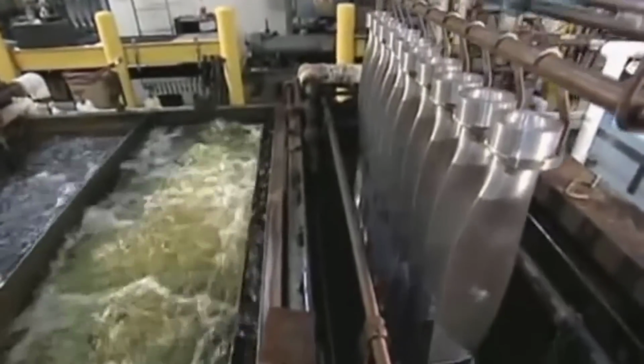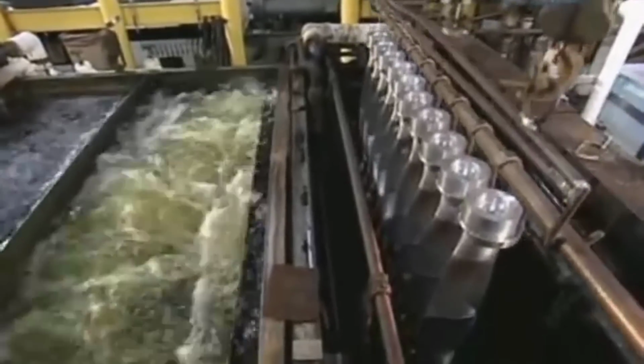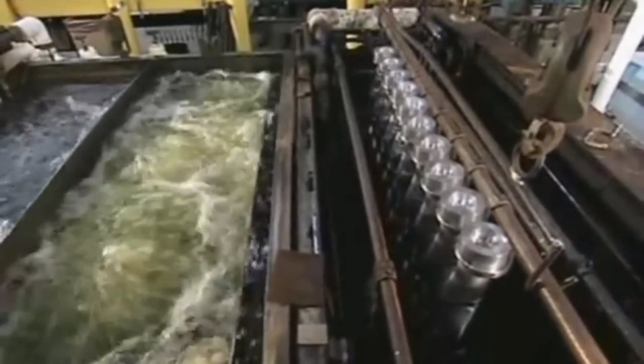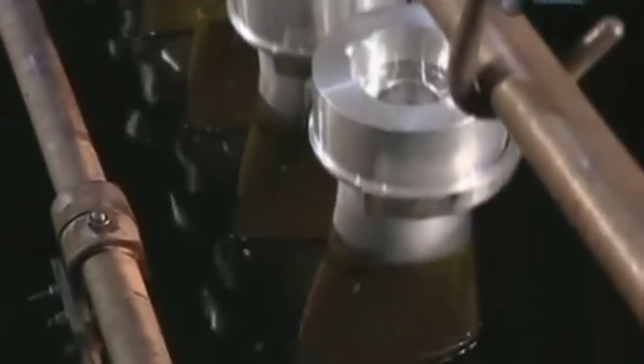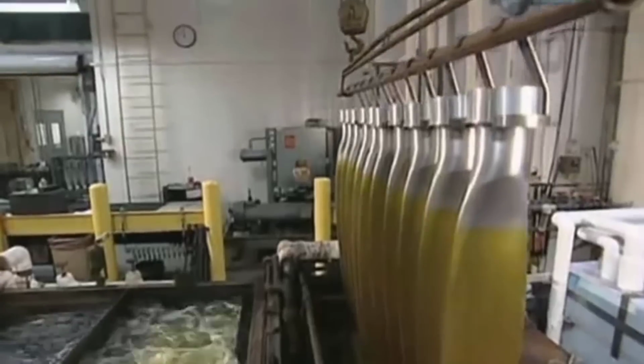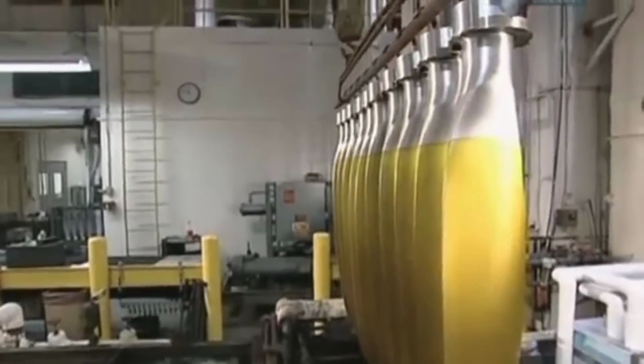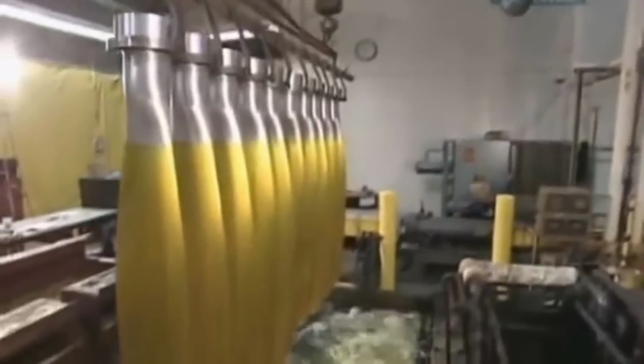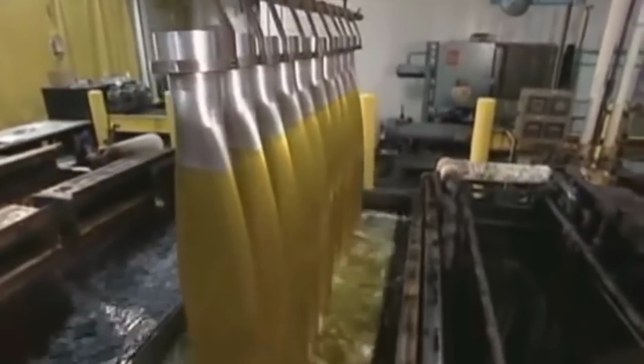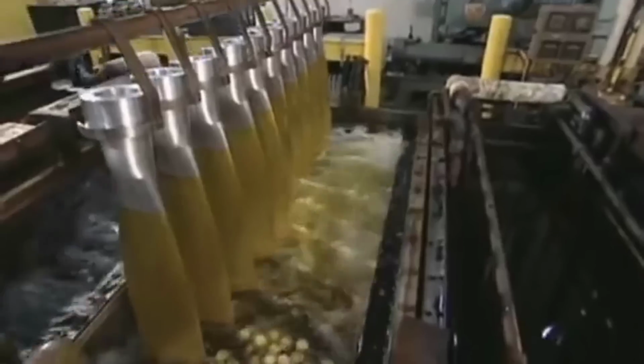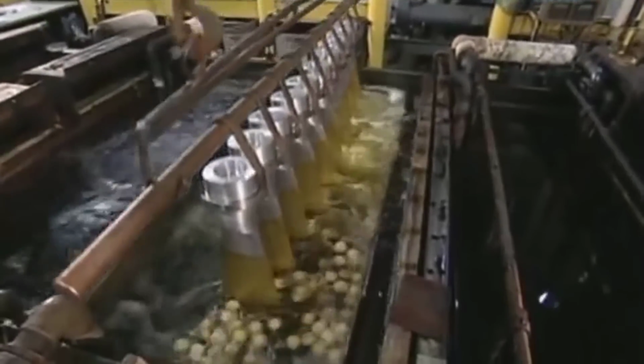The subsequent treatment involves immersing the blades in a bath of water and chromic acid, sealing the metal's pores to avert corrosion. Rigorous quality control measures include subjecting critical parts to scrutiny for surface defects using a fluorescent solution. Inspection under a blacklight distinguishes approved parts with a reassuring blue glow, while any imperfections illuminate as vivid fluorescent green, leading to the repair or rejection of defective parts.